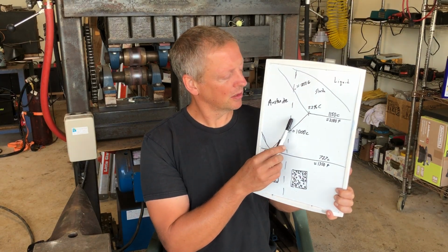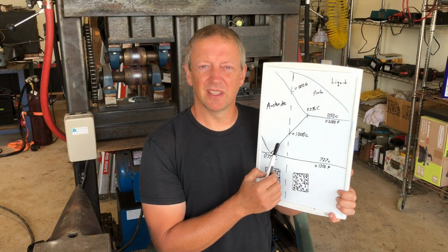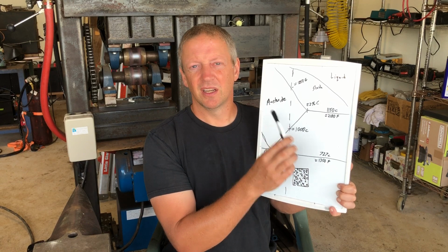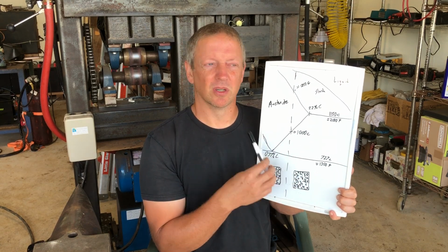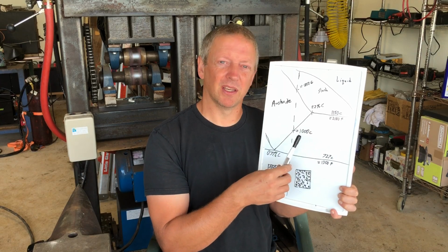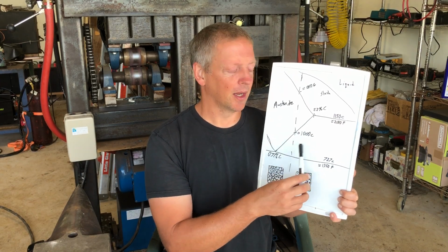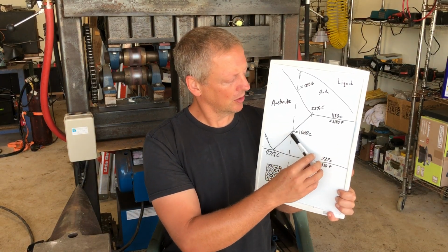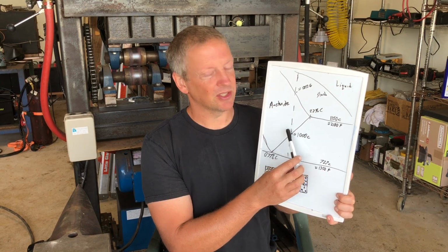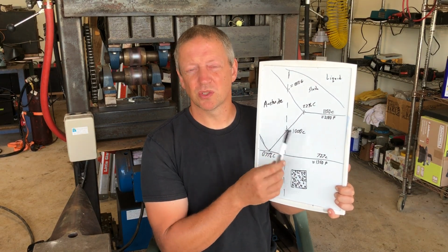If you work above the ACM line, or go above the ACM line on every forging cycle, or most forging cycles, you will dissolve more of your carbide each time. But again, it will reform as you cool. So this will tend to get you, for the most part, smaller carbides.